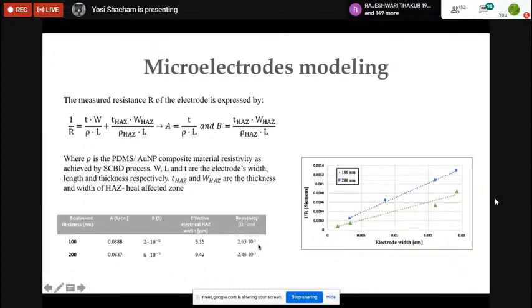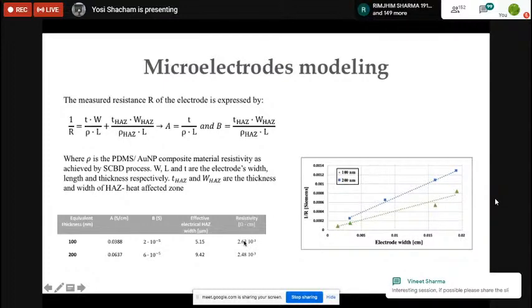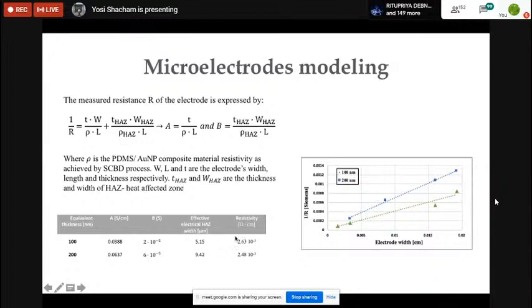It's not as good as pure gold, which would be 3 orders lower, like 4, 5 times 10 to the minus 6. But this is like polysilicon, like indium oxide, like zinc oxide. It's a pretty good material, pretty good conducting, and very, very flexible, really very flexible.